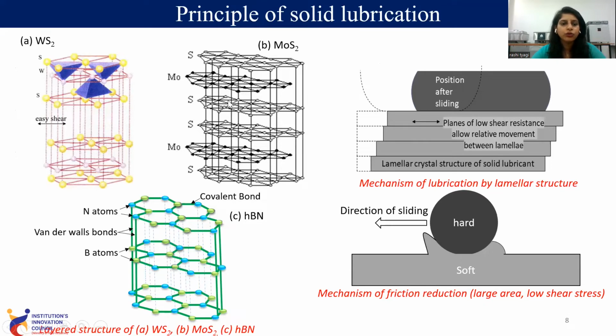Lubrication: basically these are the WS2, MoS2, and hBN lubricants, and this is how they work. They have a laminar structure, which means they are in the form of layers. There is low shear resistance between these layers, so that they can slide over each other. If they slide over each other, they provide a low coefficient of friction against other surfaces.